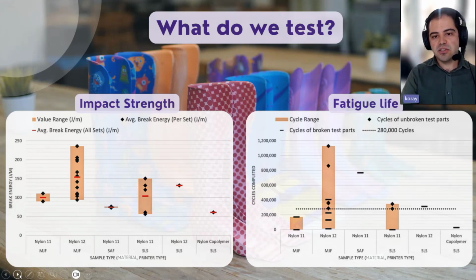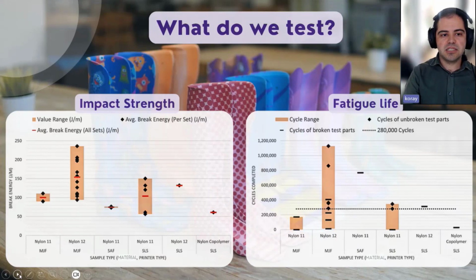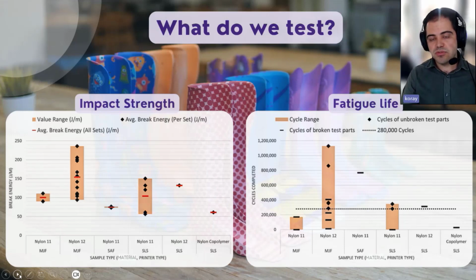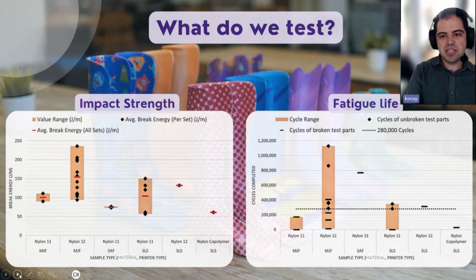We did find that with nylon 12 MJF, there's quite a big range, and at the highest range, we've got the Multi Jet Fusion 580 printers. From that we can see that those prints perform quite well at heel strike when you're running and jumping. If a client was to fall, the device does quite well in those modes. So the vapor polishing definitely helps, and that's where we could actually see the range for the same material. For nylon 12, we've got a range from 100 joules per meter to almost 250, and that range comes from the different print bureaus, the different print processes, whether it's been vapor polished or not, and also the refresh rates.